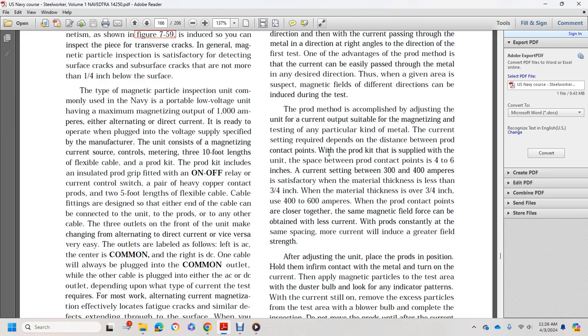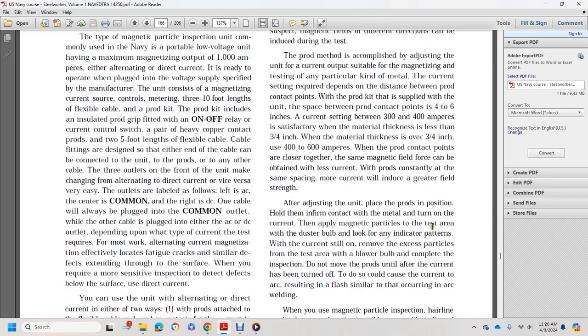The prod kit supplied with the unit spaces the prod contact points 4 to 6 inches apart. A current setting between 300 and 400 amps is satisfactory for material thickness less than 3/4 of an inch. When materials are over 3/4 inch, use 400 to 600 amps. With the prod contact points closer together, the same magnetic field force can be obtained with less current. With the prods constantly at the same spacing, more current will induce greater field strength.